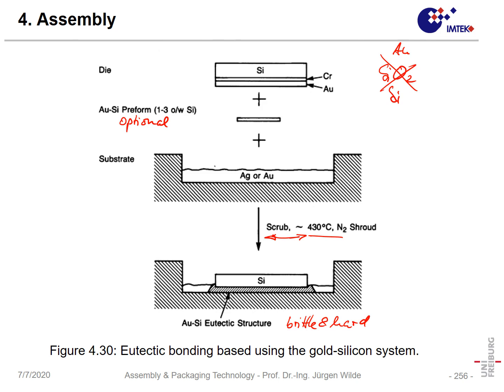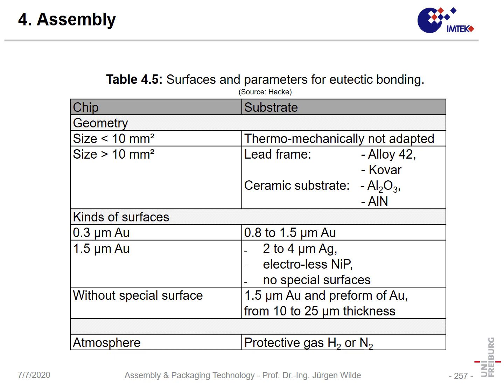So it cannot give relief against thermal mechanical stress, and that means that is a process which is extremely stable, but it can also be a high stress process. So if the substrate and the chip are not thermomechanically adapted, you can only go for small chips. If you want to have larger chips, you take something which is compatible with silicon, so it could be Alloy 42 or Kovar, or you use something like aluminum nitride, which is very close to the silicon in CTE.